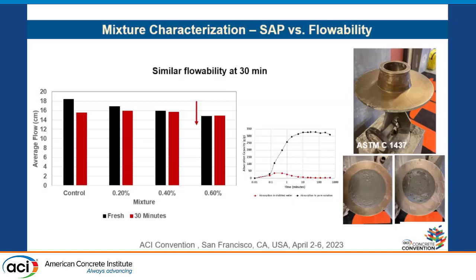We use ASTM C1437 for now, just as a very quick estimation of our flowability and the flow range, and we realized that SAP at different contents, 0.2%, 0.4%, and 0.6% of the cementitious material, decreased the flowability to some extent. But of course, this was for the fresh mixture immediately after mixing. But after like 30 minutes, we had more constant values for flowability comparing the control sample and the ones with SAP, which is mostly because the hydration of the control sample was very quick, but with SAP, because of the gradual release, the hydration was kind of delayed.